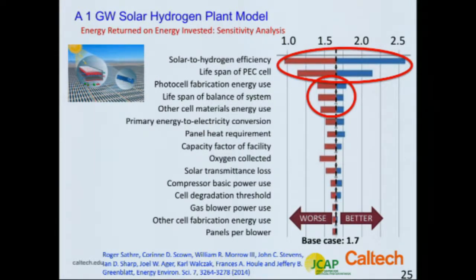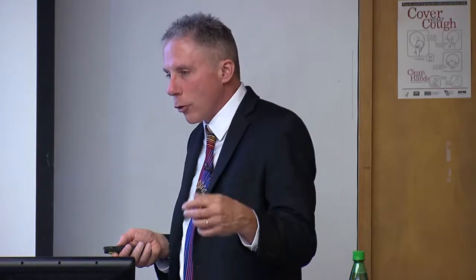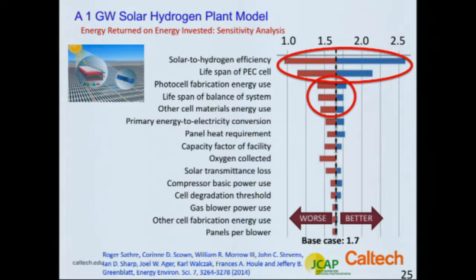And the good news is it has an energy return on energy invested—that was the metric used, not financial return—greater than 1. It would have been depressing if it were less than 1. In fact, the factors most leveraging how much bigger than 1 you can get... by the way, the payback time for the device I showed you in the prototype, if you directly took that first generation device and did this, would be about 8.5 years. So if we could make the device last 30 years, that would be interesting—I need to talk to Roger about this. But the factors we're most leveraging on the economic return and the energy return are the efficiency and the lifetime. That's good news for researchers—those are the things we like to work on.